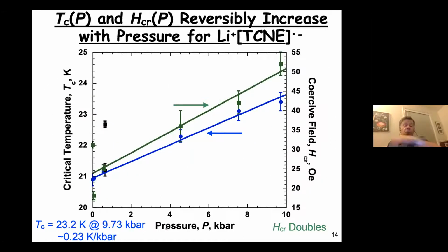And here we have in blue, the magnetic ordering temperature goes up from 21 degrees to 23.2 degrees Kelvin, up to 9.73 kilobars reversibly at an average rate of approximately 0.23 kelvins per kilobar of pressure. The coercive field doubles, as you can see in green, as you go up. And in both cases, by releasing the pressure, both values go back to where they originated from at ambient pressure. So it's a reversible pressure dependence for this material.